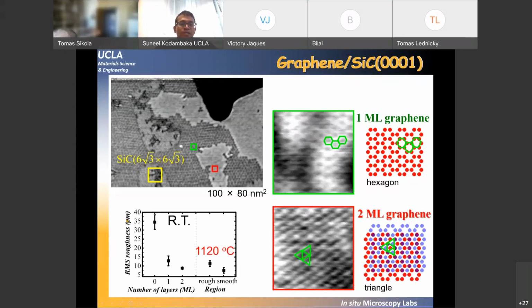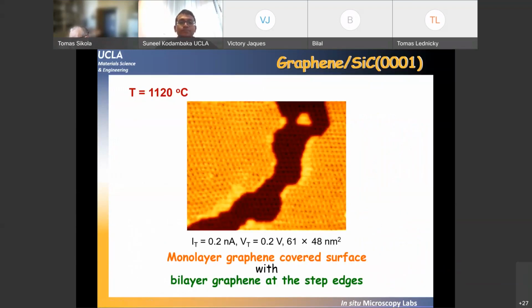And it turns out that the surface roughness depends on the phase. So for the 6√3 by 6√3 phase, you have higher roughness than for bilayer graphene. And this seems to be the same either at room temperature or from the STM images obtained while annealing at 1120 degrees Celsius. It's also about the same. So we use this to follow the growth of bilayer graphene. This is a representative scanning tunneling microscopy image obtained while annealing at 1120 degrees C.